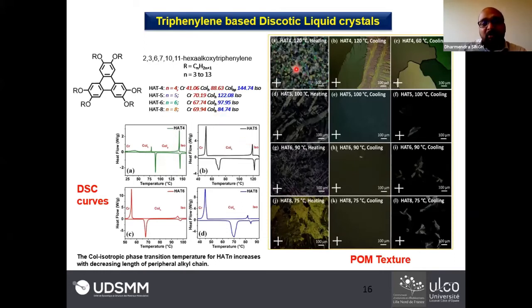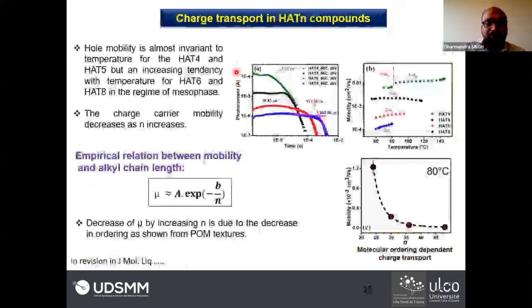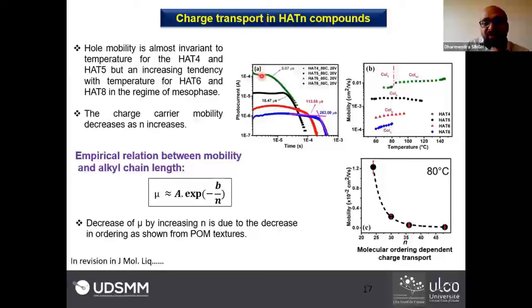We can determine the molecular ordering in these molecules under the polarized optical microscope. You can see here the optical micrographs of each of these homologous members. I would like to tell you that for HAT4, 5, 6, and 8, when you increase the alkyl chain length, the molecular ordering reduces, because the alkyl chain nature is temperature dependent. When you increase the temperature, these are thermally unstable, and they hinder the charge transport in this type of molecule. We have recorded different photocurrent curves for the triphenylene molecules, and you can see from HAT4, 5, 6, and 8 that the photocurrent curve decreases. If it changes, you can also find a change in the transit time, and depending on the transit time, your value of mobility will change.